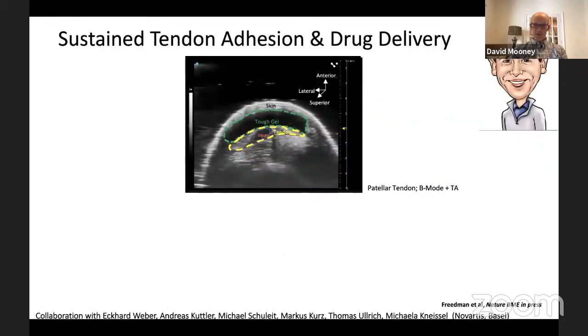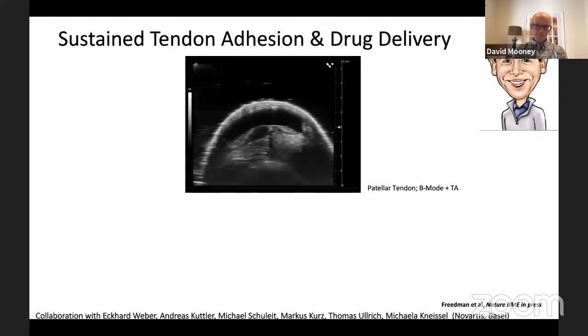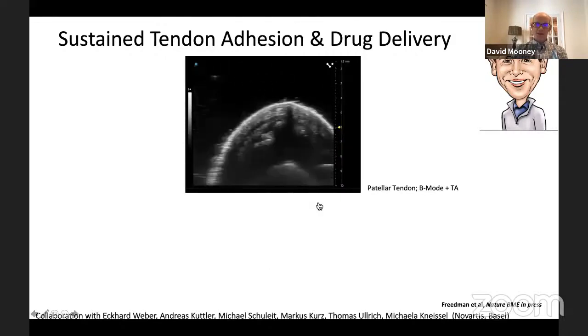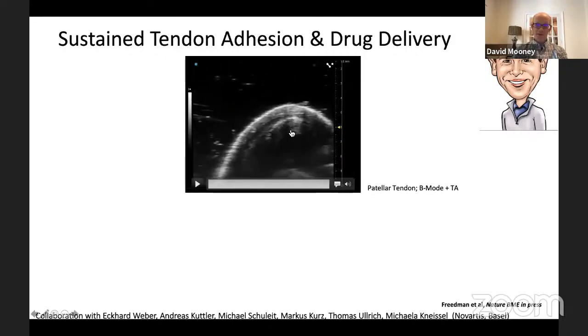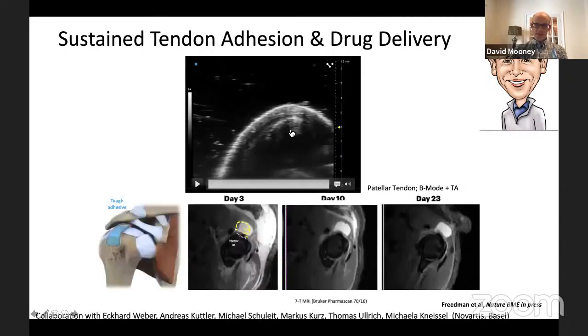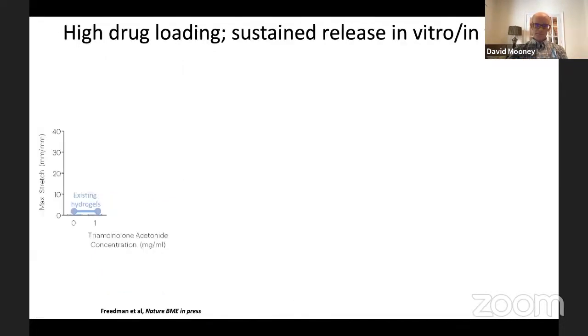So to pursue this, Ben, and here's just an image of Ben, has been working with colleagues at Novartis, led by Eckhard Weber. He's been placing these, for example, here you see one placed in a patellar tendon above a defect site. They've demonstrated that not only can they place these on really demanding sites like a tendon, but they will actually stay in place for several weeks, as indicated by the imaging you're seeing in the bottom.